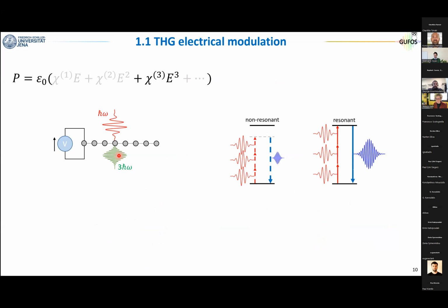We now take a graphene and we look at the third harmonic generation. So when we take the polarization, we will look at this term, that is the chi3. And third harmonic generation is a process where we arrive with fundamental photons at energy h bar omega 0 and generate photons at 3 h bar omega 0. Now consider that chi2 is 0 in graphene because graphene is centrosymmetric, and this term exists only in non-centrosymmetric crystals.